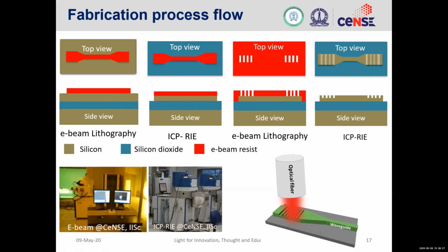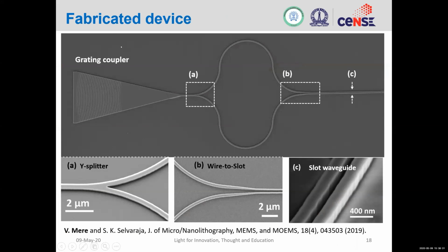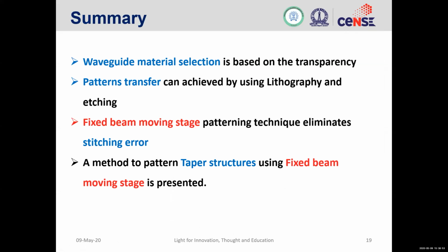By following the same procedure, we fabricated photonic integrated circuits. Here I'm showing a Y splitter, where this kind of structure can be used to split light, and this kind of wire-to-slot structure is used to combine light into a single waveguide. In summary, I have explained the criteria for selecting a waveguide material, which is based on transparency, and then how lithography and etching can be combined to transfer a pattern onto a substrate. Then we explained the fixed beam moving stage patterning technique, which eliminates stitching error. And finally, I have presented a patterning method using only FBMS.